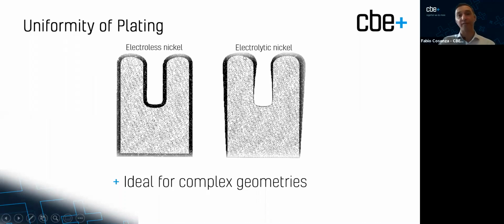So this is a magnified view of a complex geometry part. The distances here are really microscopic, but you can see from the picture on your left how uniformly electroless nickel has applied itself to the surface of the part. Whereas you can see electroplating, due to the currents that are generated inside the bath and on the part, will want to accumulate in certain places. You know, electroplating loves sharp corners, and then you can see how non-uniform the plating has been applied. So electroless nickel makes it really ideal for application on complex geometries, such as really highly engineered parts.